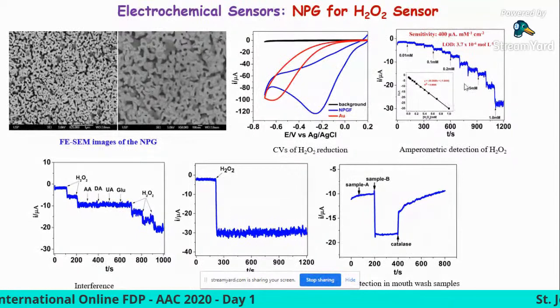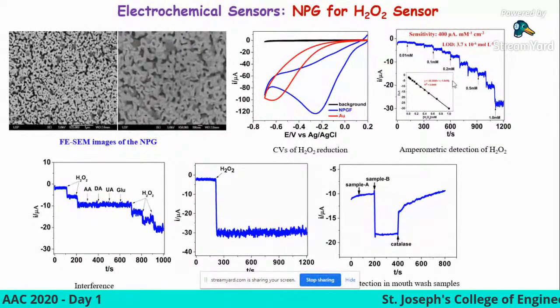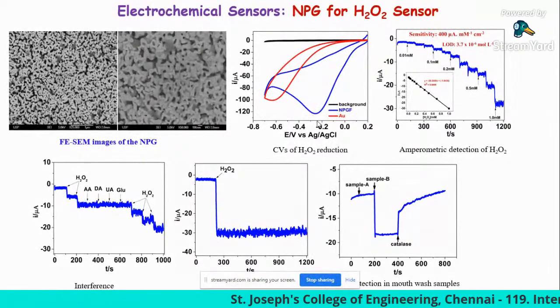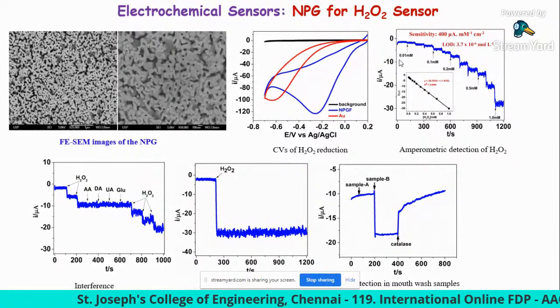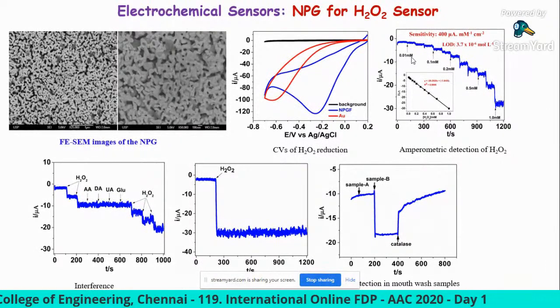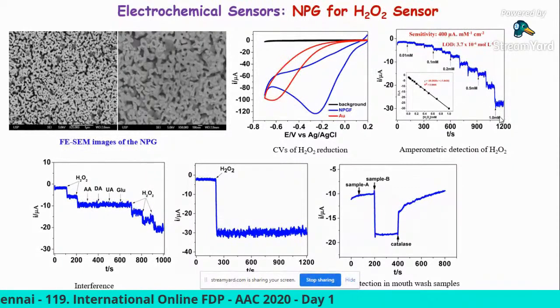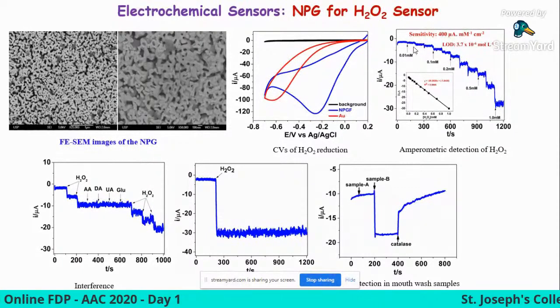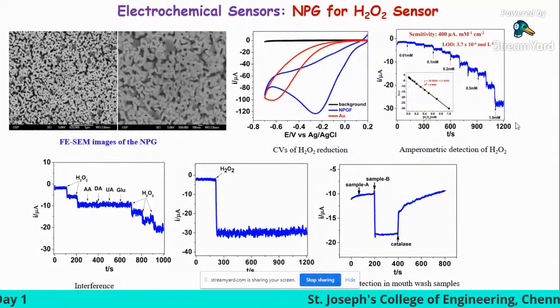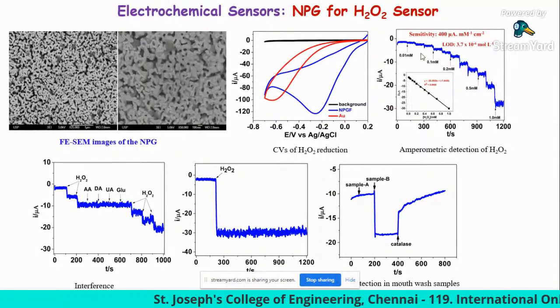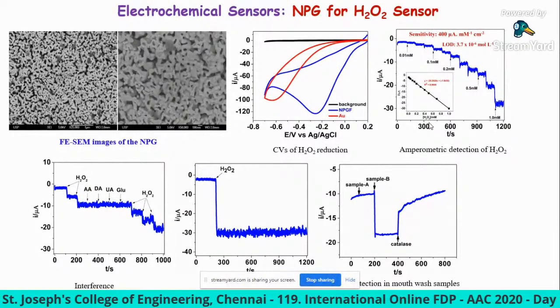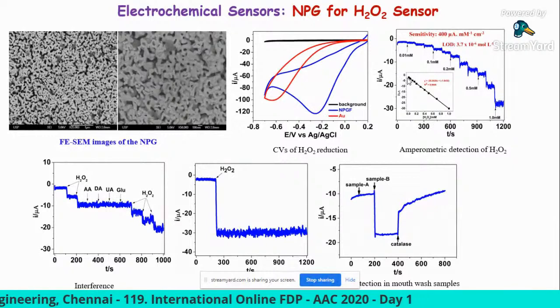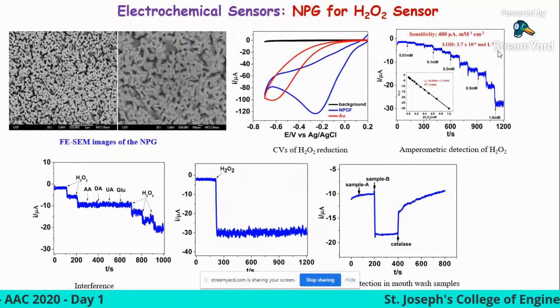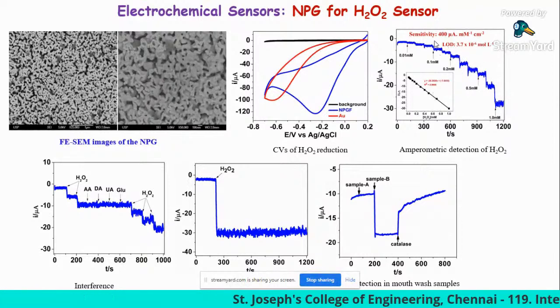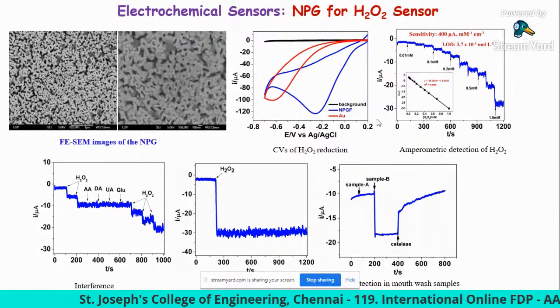So this is the amperometric response of hydrogen peroxide reduction at an applied potential of minus 0.2 volt from 0.01 millimolar, that means 10 micromolar, to 1 millimolar. Whenever you add the hydrogen peroxide, the current signal keeps on increasing. Then if you plot the current signal with respect to the hydrogen peroxide concentration, you can get linear behavior. From the slope of the curve, one can calculate the limit of detection as well as the sensitivity of the electrode.